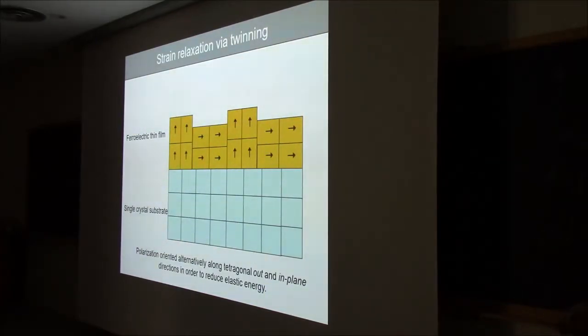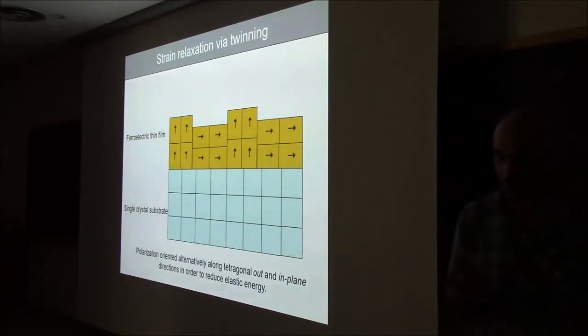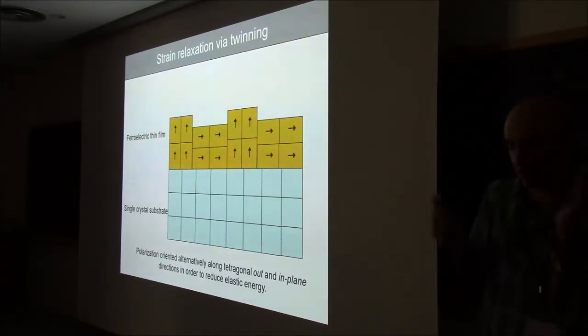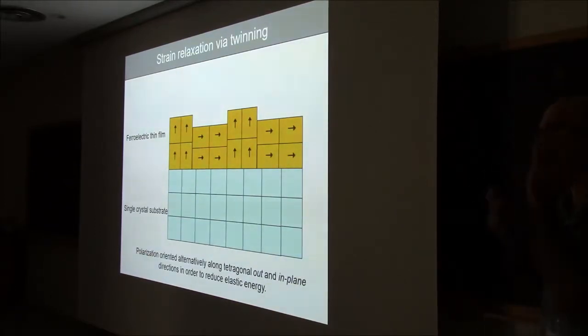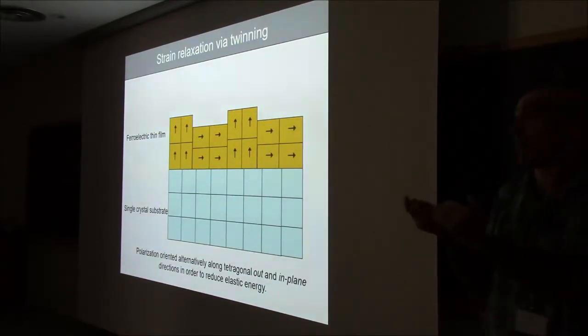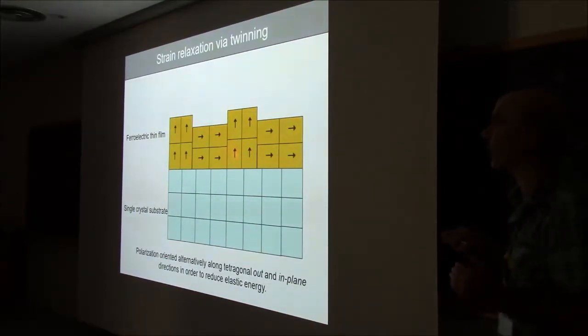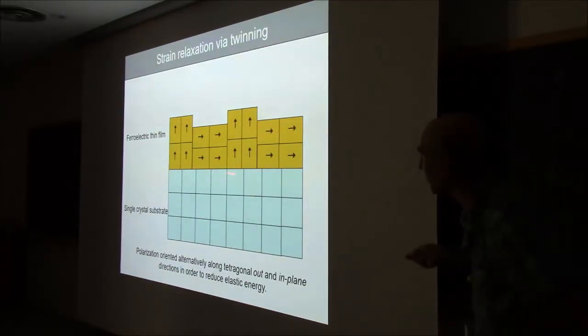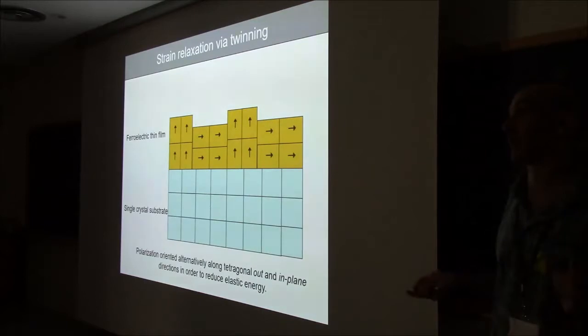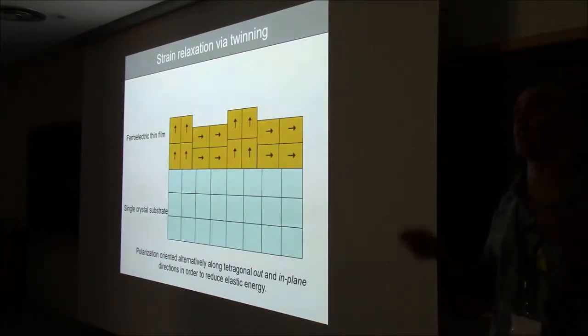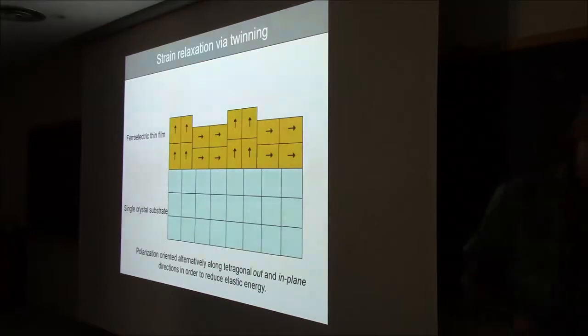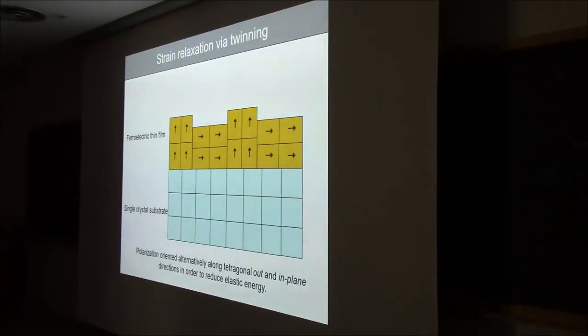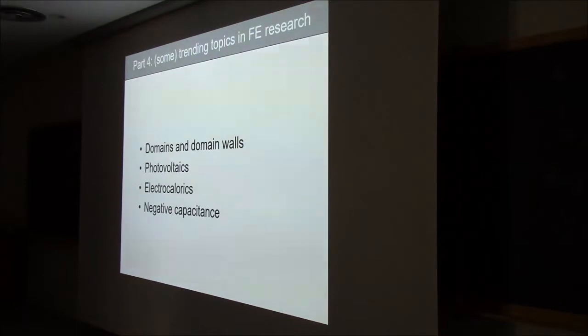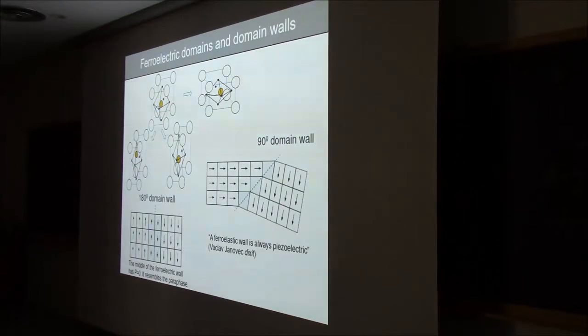In reality, however, if you try to play this game, what you will find is that your material breaks into domains. So there's a fine line when changing the symmetry of your material. Something that would have liked to be tetragonal, you're asking it to be monoclinic. Sometimes you manage, and it will be monoclinic, but sometimes it will break into tetragonal domains such that the average lattice parameter coincides exactly with the lattice parameter of the substrate. And then you haven't changed the symmetry, you just changed the domain configuration. This is something you should know about ferroelectrics, that they have domains. And there will be a talk about domains by Lane Martin, I think, on Friday. But just to warm you up for it,